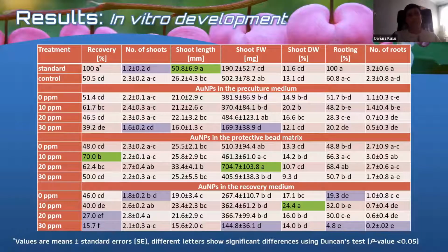But so far, we have learned that the addition of gold nanoparticles significantly affected the successfulness of cryopreservation, although the effect of these nanoparticles depended on whether they were added to the pre-culture medium, to the recovery medium, or to the alginate bead matrix. And we found that when adding gold nanoparticles at low concentrations to the alginate bead, to the capsule, the efficiency of cryopreservation, the recovery potential, increased by 20%. And also the plants which were recovered from the capsules that contained gold nanoparticles had the greatest fresh weight.